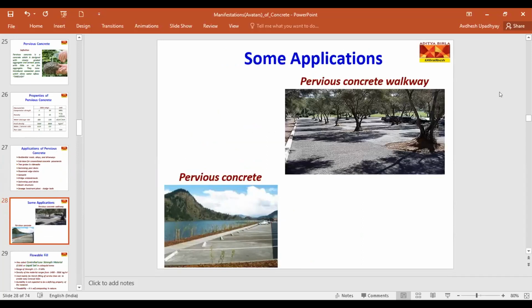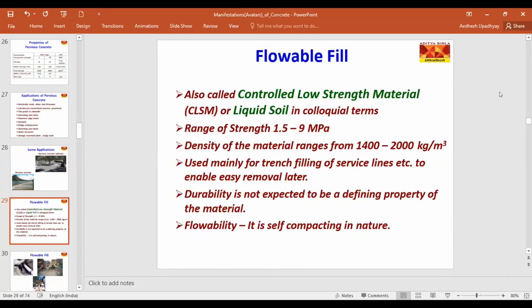Then the next one is flowable fill. This concrete is basically controlled low strength material, or liquid soil in colloquial terms. Strength is 1.5 to 9 MPa. Density is 1400 to 2000 kg per cubic meter. It is mostly used in trench filling. Durability is not a criterion, but we require flowability, so it is self-compacting in nature. These are some pics of flowable fill. It is used for trench filling.